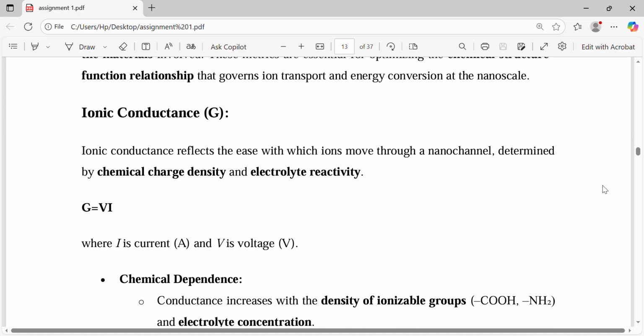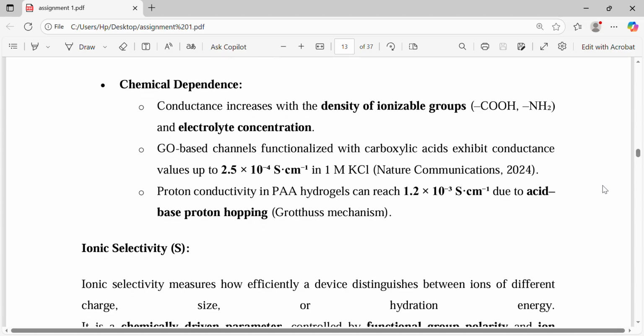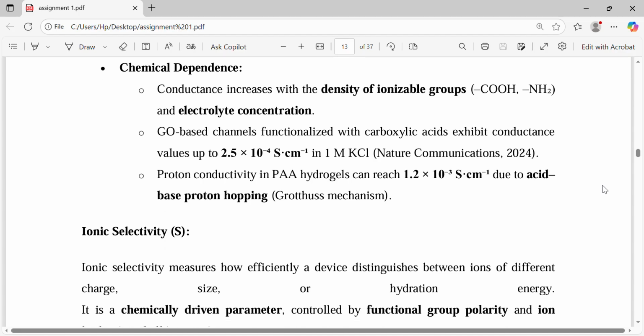Ionic conductance. Ionic conductance reflects the ease with which ions move through a nanochannel, determined by chemical charge density and electrolyte reactivity, where G = I/V, I is current and V is voltage. Chemical dependence: conductance increases with the density of ionizable groups. GO-based channels functionalized with carboxylic acid exhibit conductance values up to 2.5 × 10^-4 S·cm^-1. Proton conductivity in PAA hydrogels can reach 1.2 × 10^-3 S per centimeter due to acid-base proton hopping.